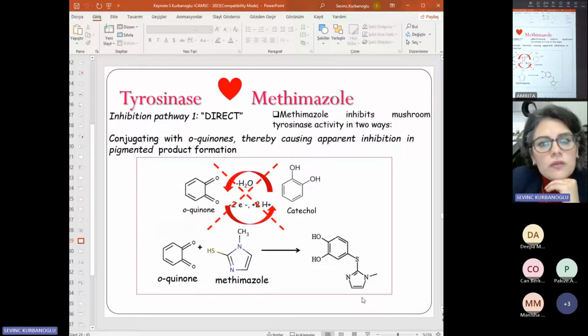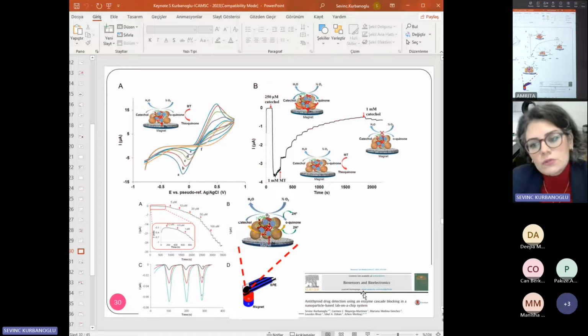And when we searched, we saw that the methimazole drug can inhibit tyrosinase. And how does it inhibit? It can inhibit directly in the first pathway. It can conjugate with orthoquinones, thereby causing an apparent inhibition in the pigment product formation. And if we can follow this electrochemically, it will be very nice for us.